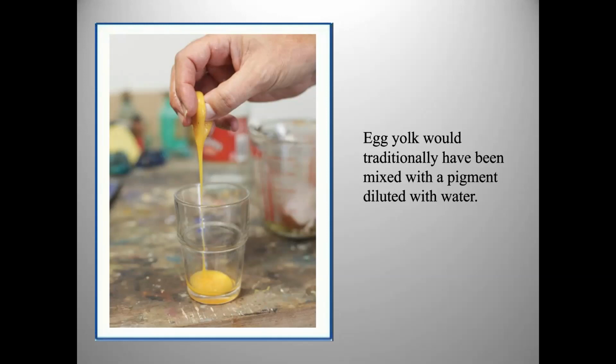The commercial paints were liable to contain strong preservatives or disinfectant to prevent the egg from going bad, and these disinfectants sometimes had a detrimental effect on certain colours. The acidity of the acetic acid, the vinegar, would have detrimental effects on both the paint layer and the paper support, as acid solutions will attack chalk or whiting grounds, ultramarine blue and the cadmiums.